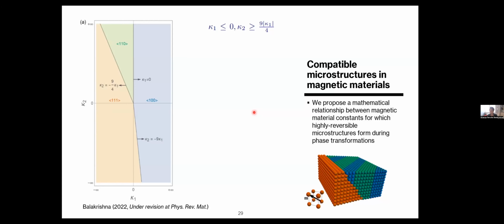And so that was the line of work that we're looking at, and is a work that is being currently revised. But we identify a mathematical relationship between material constants. If one is to stabilize a highly reversible stress-free interface, for which you can take the magnetic material between paramagnetic and ferromagnetic phases and cycle them repeatedly and reversibly, one needs to ensure that the alloy has a combination of anisotropy constants that satisfy the constraint over here. So if you were to plot this on a plot with kappa 1 and kappa 2, which are your 2 anisotropy constants, if you want to tune a specific alloy which has ultra low fatigue, you would want to work in this region where your K1 is less than 0, but your K2 satisfies this constraint.